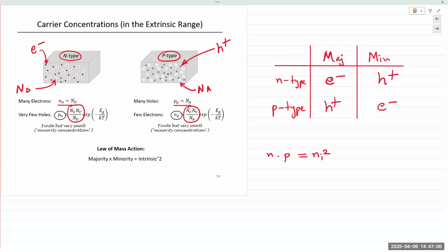That's a phenomenon that was observed very early on. The rate of generation and recombination is doing the cycle constantly. Even if it's just sitting on the desk, a small piece of semiconductor silicon is constantly generating and recombining electrons and holes. So this rate remains near constant, so it's electrically charge neutral. So n times p equals ni squared, and that governs intrinsic semiconductors as well as extrinsic semiconductors.